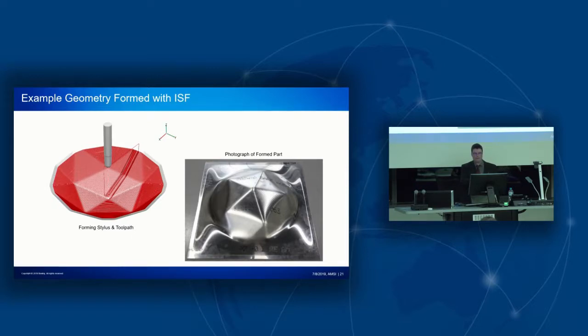So here you can see a toolpath that we've cut. It's of a truncated icosahedron, so it's kind of a generic complex part that we chose for the purposes of validation. Now, this is not a part, I should mention, that we would actually think it's acceptable to put on any sort of vehicle. We chose the single point incremental forming method because it actually has the most freedom to deform, and it's significantly out of tolerance when you compare it to the part for most geometries. So this is actually the most challenging process that we could try to simulate.